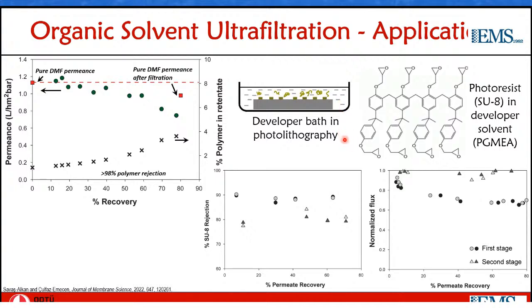So we prepared representative solutions of SU8 and PGMEA, and again filtered this in dead end until a permeate recovery of 80%. We had a rejection of close to 90%, and the flux declined down to about 60% of the pure solvent flux. And then we collected this permeate and fed it again to the same membrane to simulate a second stage filtration with the same kind of membrane. What we observed was a somewhat smaller rejection, but a fully recovered flux, as in the second stage, the flux was essentially the same as the pure solvent flux. So here again, we could obtain close to 95% overall rejection, starting from the feed to the second stage permeate, and a recoverable flux at the end of this filtration process.